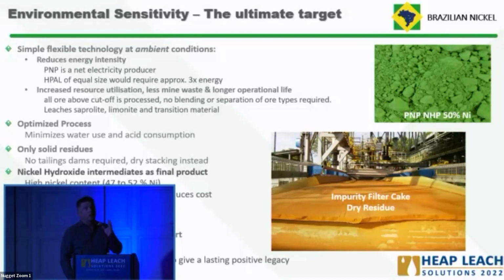Well, on the acid consumption, we also take a slightly different approach than everyone else. One of the preconceptions of nickel is that it's a high acid consumer, and in fact it is. So the acid plant or the acid supply becomes your constraint. So we work the other way around. We define what is the acid supply capacity that we can do, and then we match everything else backwards. So instead of us defining a fixed target extraction, we said with the amount of acid that we have, what is the extraction that we can get? And we do the mine planning accordingly, targeting obviously the highest grades.